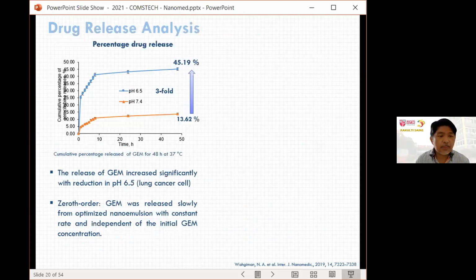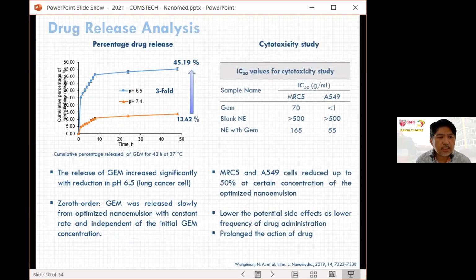When we talk about the drug release, it is almost threefold at pH 6.5. And if we relate this to the cytotoxicity study, it showed that the optimized nanoemulsion containing gemcitabine induced cytotoxicity toward the A549 lung cancer cell, and at the same time reduced the cytotoxicity towards the MRC5, which is the healthy cell.